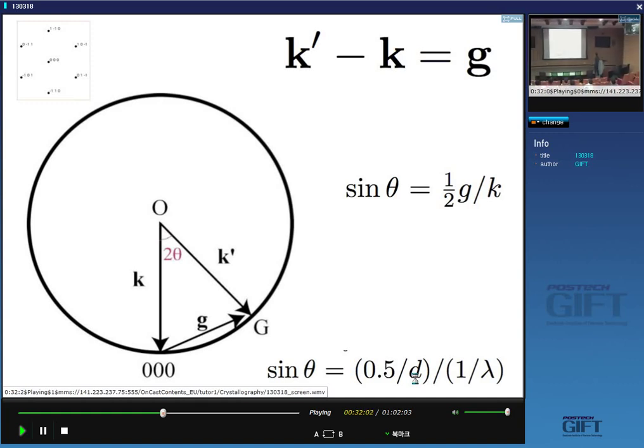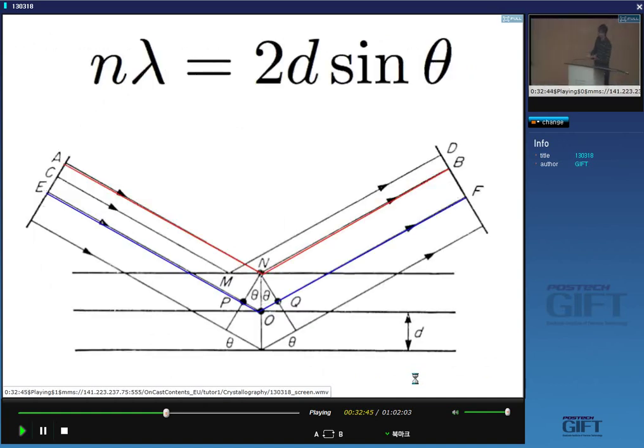Now, all you have to do is substitute 1 upon lambda here, 1 upon lambda here, and 1 upon d here. And from this triangle, you can see that sine theta is equal to half of g divided by k. Yeah, it's an isosceles triangle. k and k dashed are equal because we are only talking about elastic scattering, which means the wavelength doesn't change during diffraction. Okay, so if k and k dashed are equal and the angle between k and k dashed is 2 theta, you can see that the angle between the incident beam and the diffracted beam is 2 theta here.